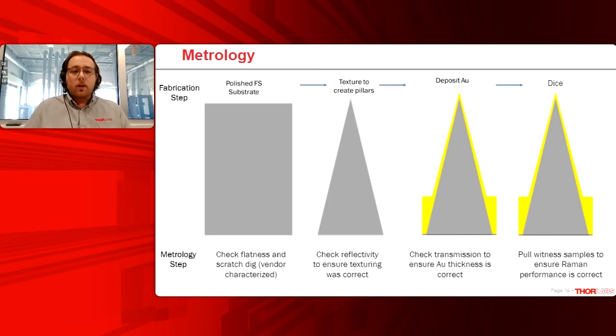So to do that, we developed this metrology set of steps where we take our quartz wafer in, and we have to check the flatness and the scratch dig specifications on that wafer to ensure that it's going to be pristine across the entire surface. We then texture the wafer, and we will measure the reflectivity across the entire wafer. Now, this is to ensure that the texturing was not only done correctly, but uniformly across the entire wafer. Next, we deposit some gold, and we will check the transmission to ensure that the gold thickness is not only correct, but uniform. Finally, we dice them into individual substrates, and we will pull a few witness samples, coat them in some molecules, and run a Raman test to ensure that the Raman performance is meeting the specification we've set forth and is uniform across the entire wafer again.